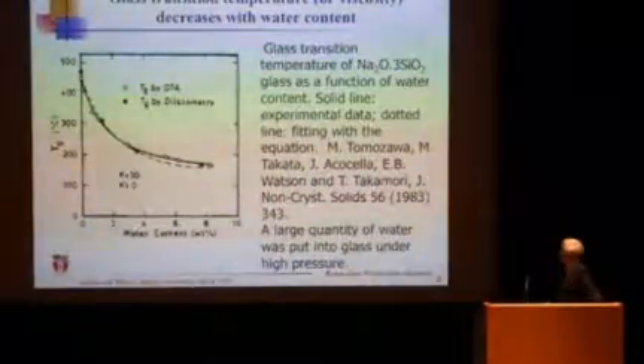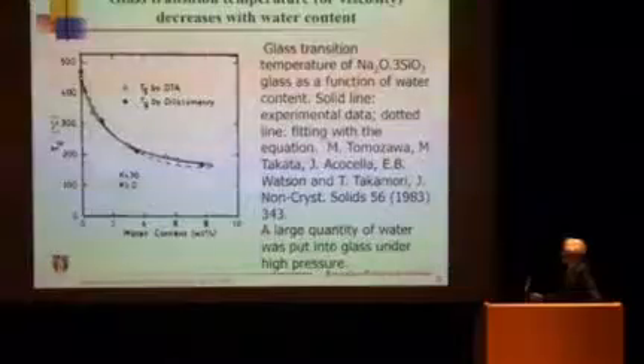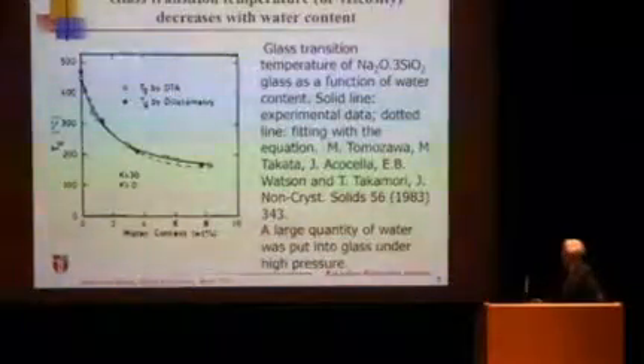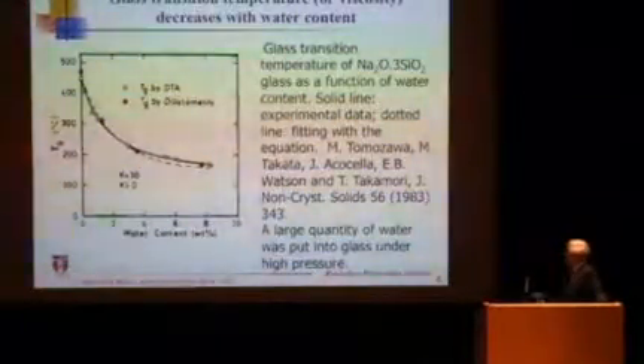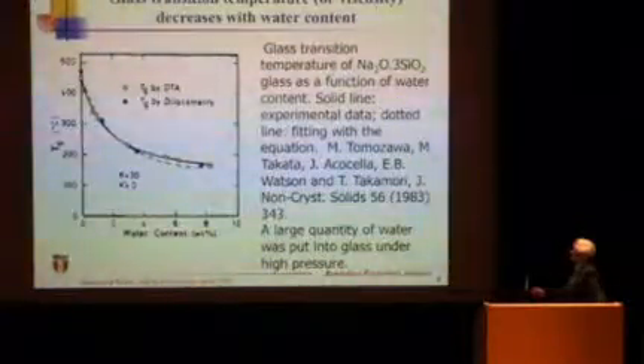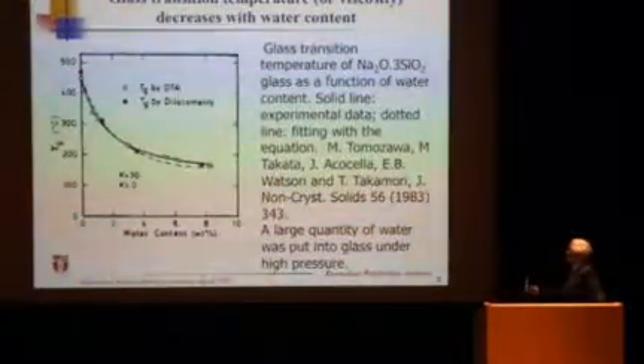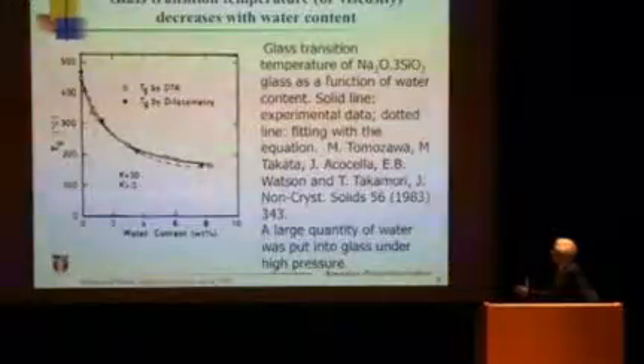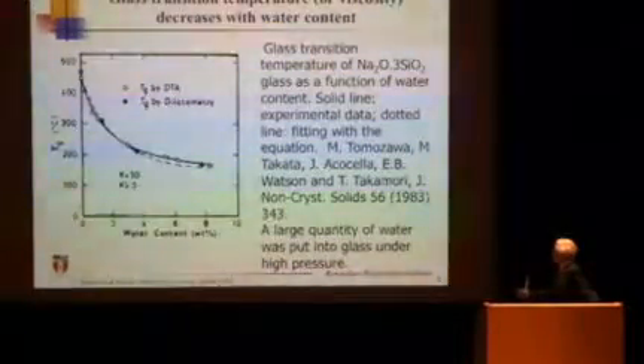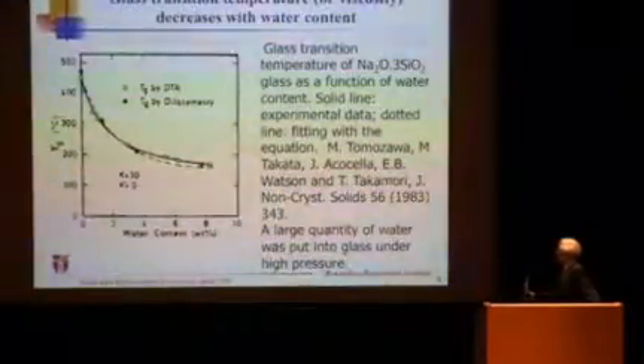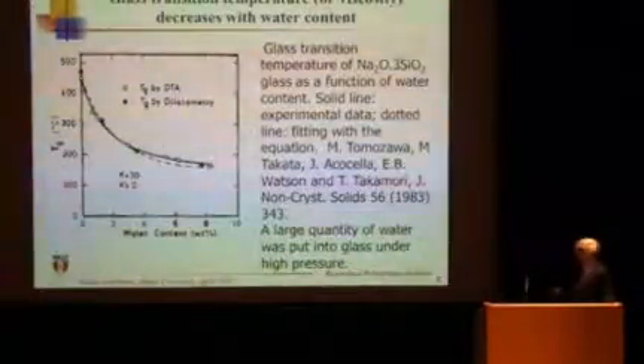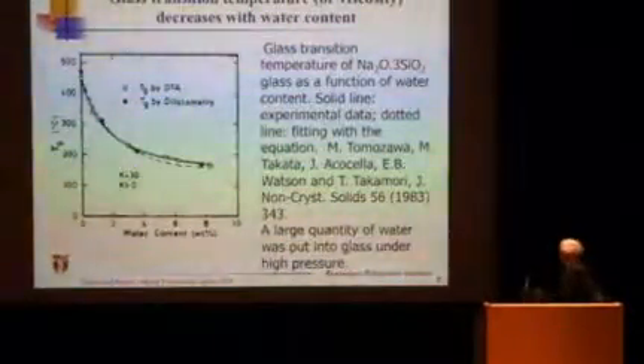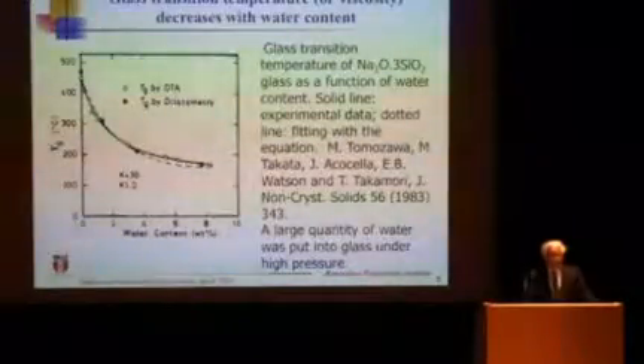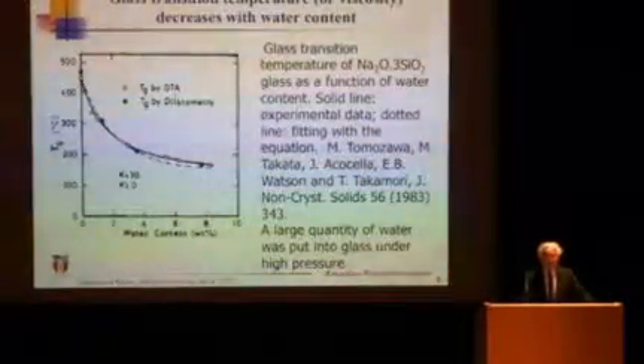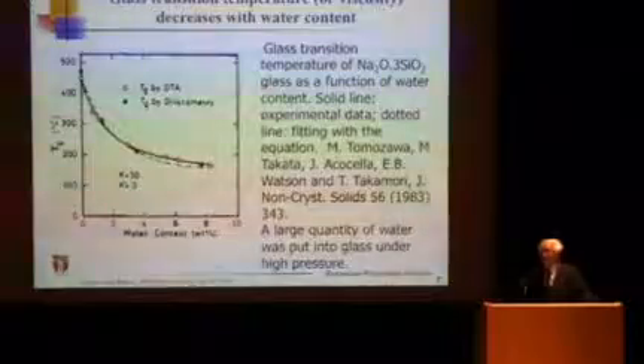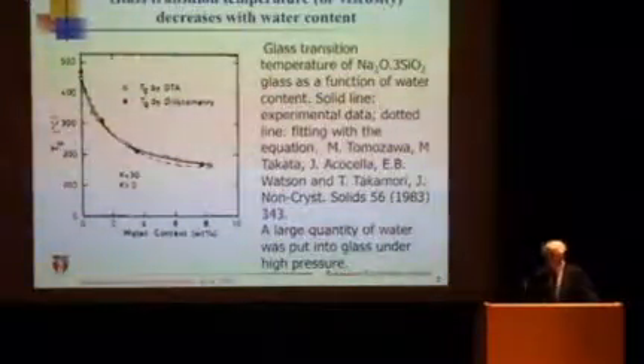So first, some 20, 30 years ago, we measured property changes with a large quantity of water. This is the sodium silicate glass, with a normal glass transition temperature of 460, 470, in that range. And if you put in water, it goes down, down, down. And we extrapolate to 100% water, that would reach the glass transition temperature of the glass form of water. So water can be made into glass too.